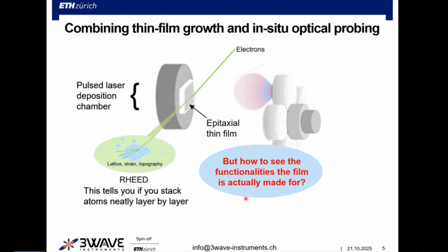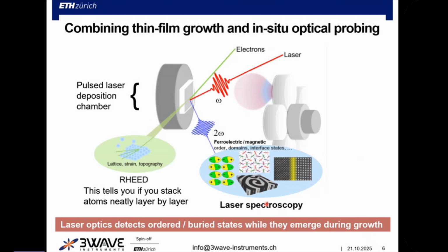Okay, so then we are back to our original sketch. So how do we see the functionality of the film while it grows? And that would now be by sending, in addition to the electron beam, a light wave, laser light at omega, nicely from the distance through the windows, non-destructive, non-invasive, and what you get back is the frequency doubled light, and that tells you about any type of order you have in your material. You can see buried states, order, while functionality emerges.